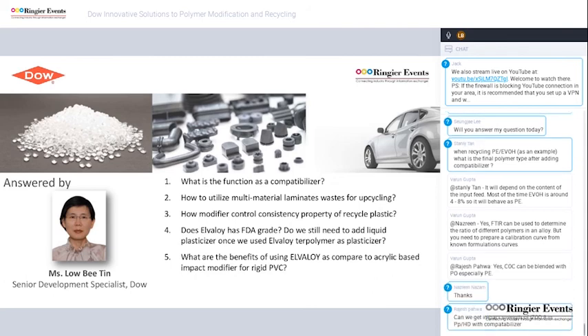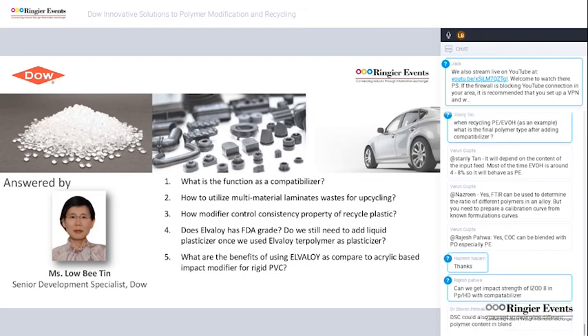We have seen that this actually provides an opportunity for cost reduction. For example, at 4% of Elvaloy 4924, it gives you a ductile failure mode, whereas acrylic impact modifier gives you a brittle failure at 20 parts of filler. The second benefit of Elvaloy as an impact modifier is that it gives you a better finish and smoother surface. This is because Elvaloy provides better compatibility between the filler and the polymer matrix.